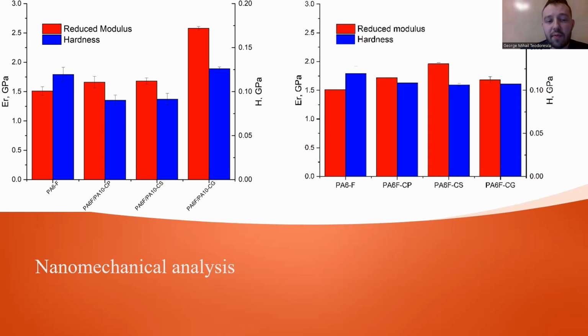So this behavior confirms the increase in flexibility because a higher modulus would indicate that the samples have a higher capacity for elastic recovery once the force of the indenter is stopped. So based on present and previous results, the silane agent acts more as a coupling agent between the fly ash and the polymer matrix.